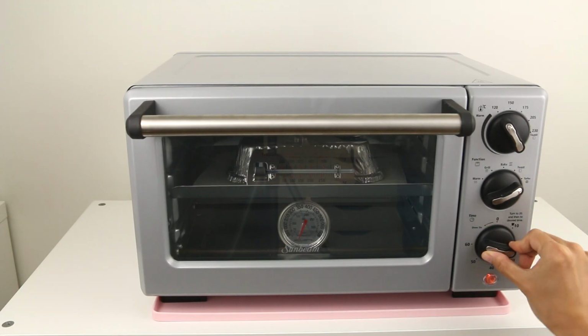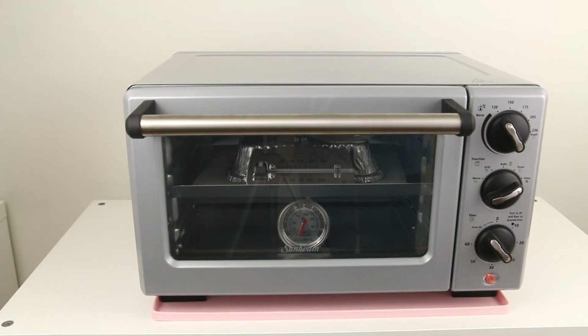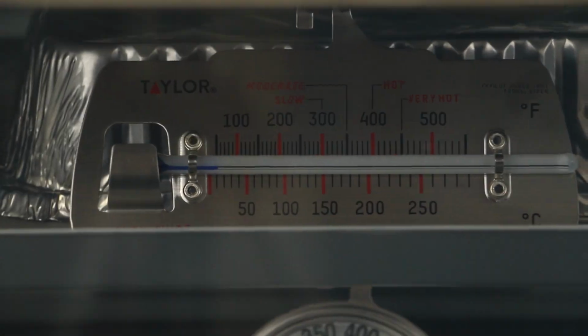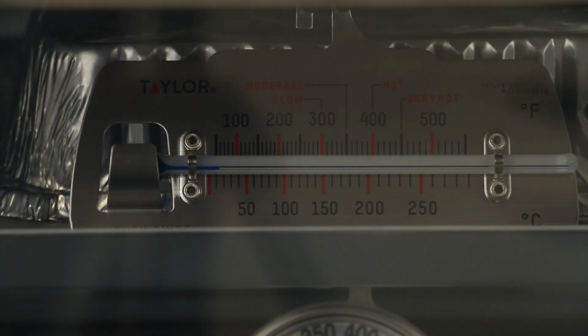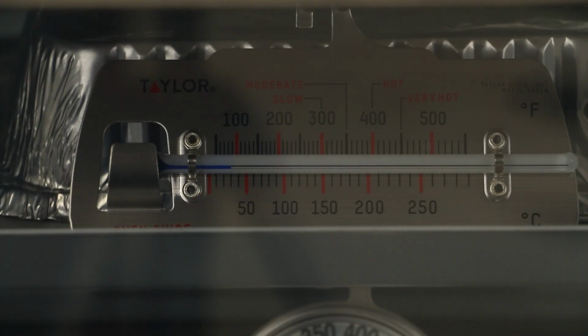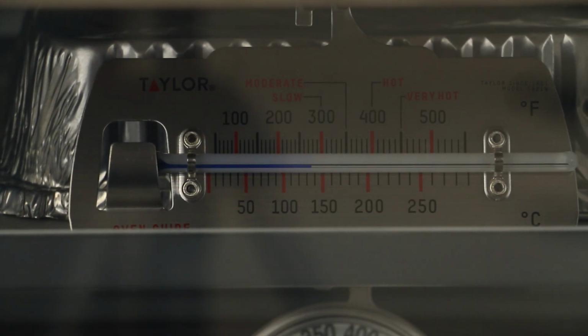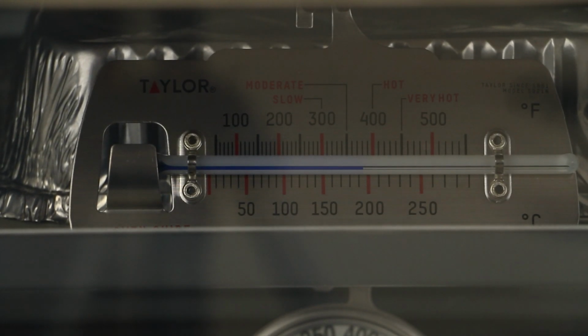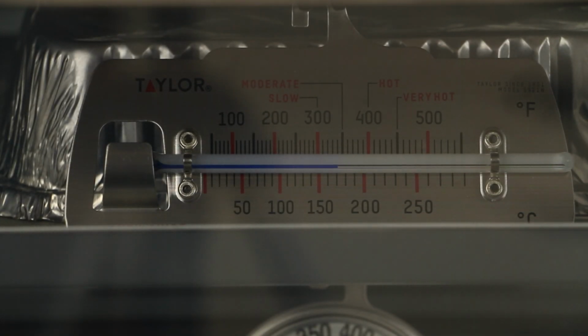To bake my charms, I preheat my oven, baking tray, baking paper and foil tent to 130 degrees Celsius or 275 Fahrenheit, and I do this for about 20 minutes on the turbo convection setting, and I make sure that it reaches temperature on my separate thermometer. It reaches a very high heat and then crawls back down to the correct temperature.